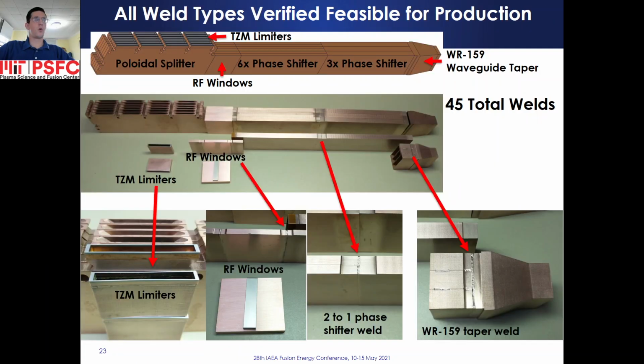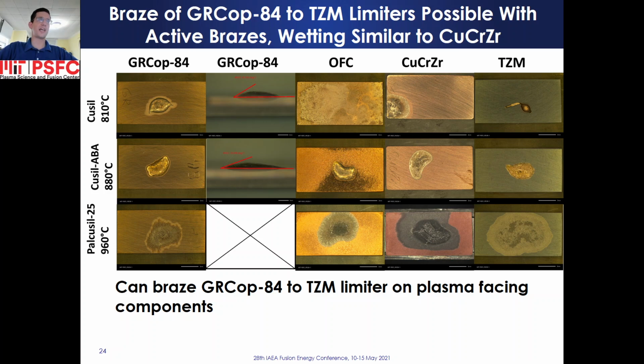All weld types in the launcher modules have been verified as feasible for production. Welds are required when joining TZM limiters brazed to GRCop-84 waveguide stubs to the end of the splitter apertures, connecting the splitter to the RF window sleeve, and assembling the phase shifter network. The phase shifters require both butt and edge welds in a 2-to-1 and 3-to-1 multi-junction configuration, as shown on the bottom. Brazing of GRCop-84 to titanium zirconium molybdenum alloy limiters is possible with the use of active brazes. Both Cusil-ABA and Palcusil-25 join GRCop-84 and TZM with excellent results.